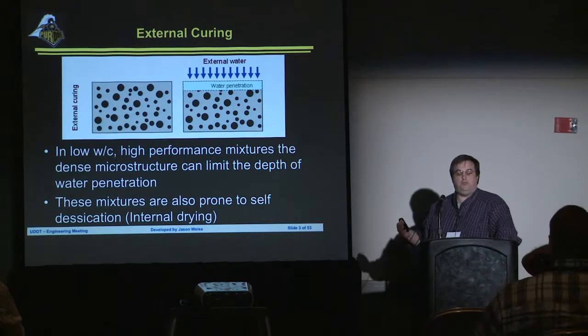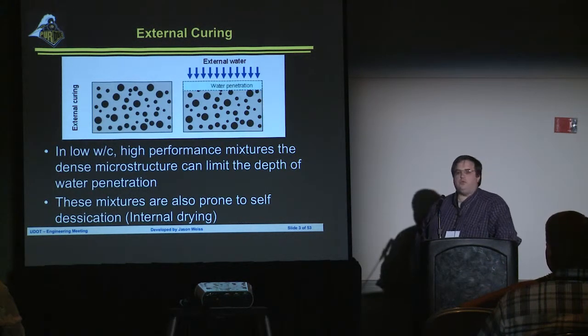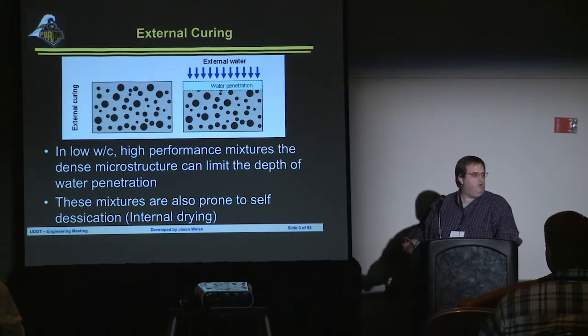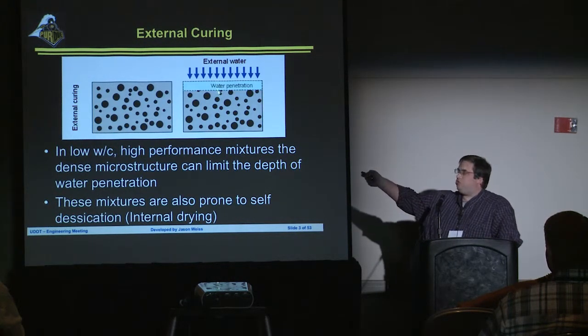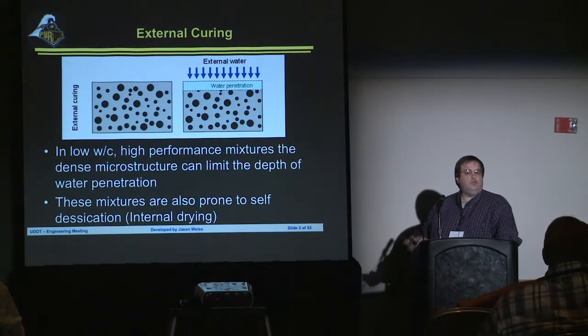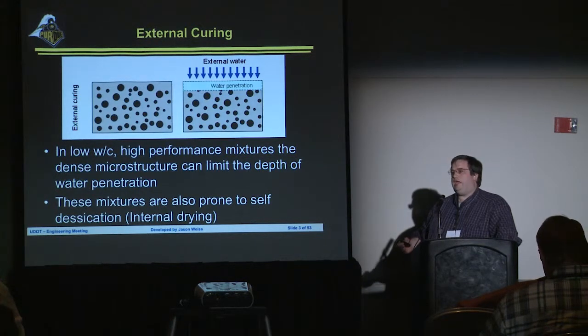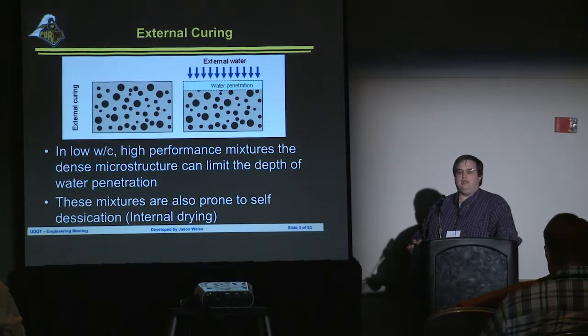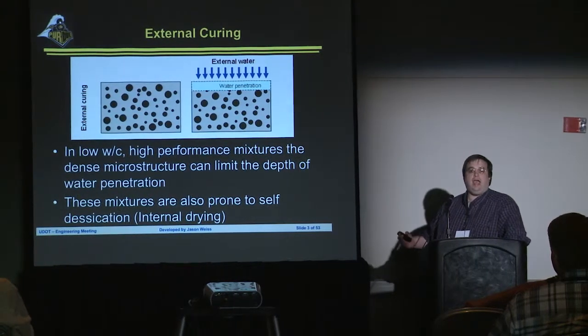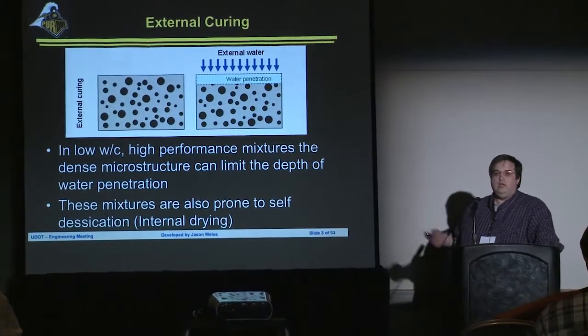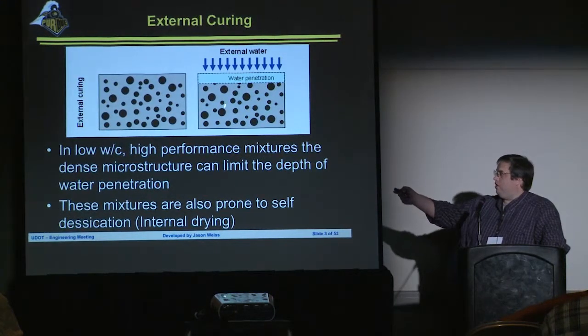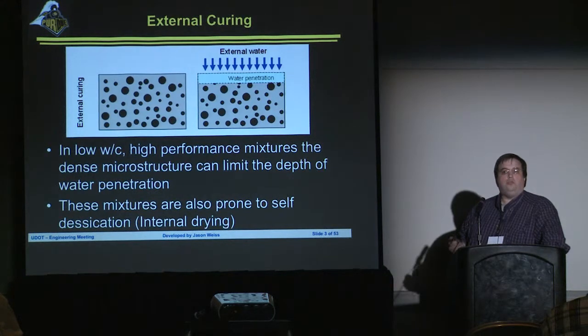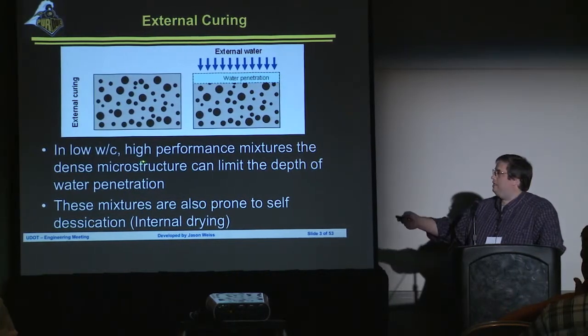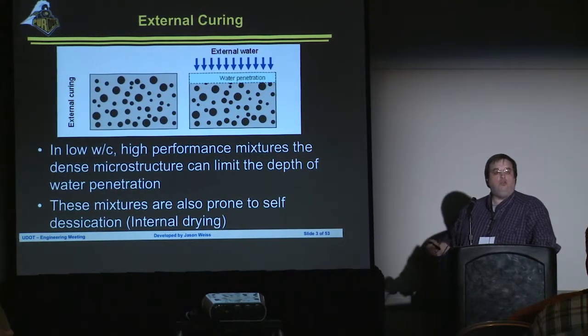While good water curing is a very useful thing, in very high-performance concretes we try to make a very dense matrix that keeps things from moving through the concrete. Just like a very dense matrix keeps chloride ions from moving through the concrete, it can also restrict the amount of water penetration. It turns out that if you use a reasonably low water-to-cement ratio concrete, you're only going to get several millimeters of water penetration after about 18 to 24 hours. So let's assume the best case scenario where we're getting 10 millimeters, or half an inch, of water penetration. We're really only curing the top surface of our concrete, and the middle portion isn't getting that additional water because we're making the system so dense. So what we're trying to look at is whether there is a way that we can make these mixes more uniformly cured.